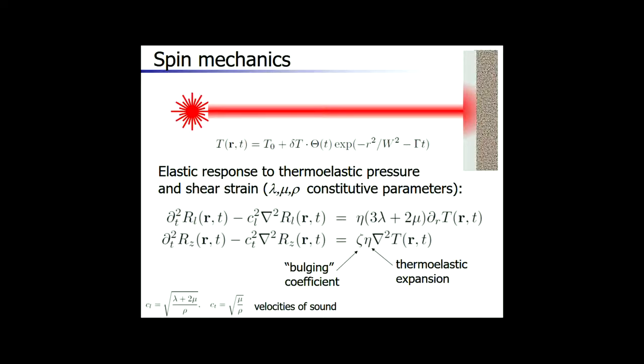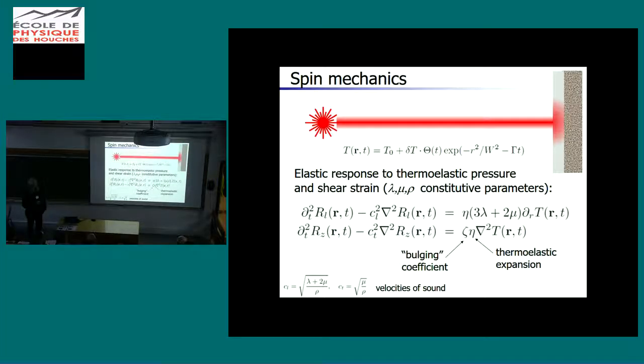So what are we doing here? This is the laser which comes in and hits the thin film. And usually it is a very fast laser. That means it's basically a theta function type of temperature increase. It has a certain spot size, which is governed by the focusing, which is of the order of microns. And there is some decay time, which we take to be long later.